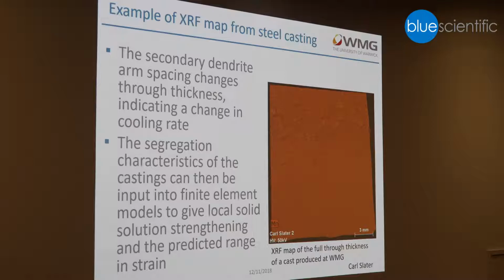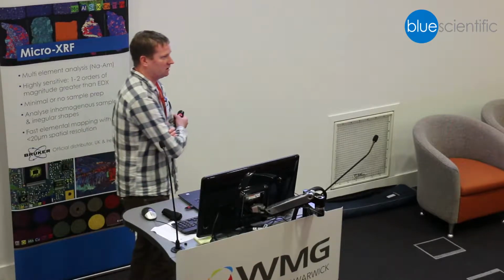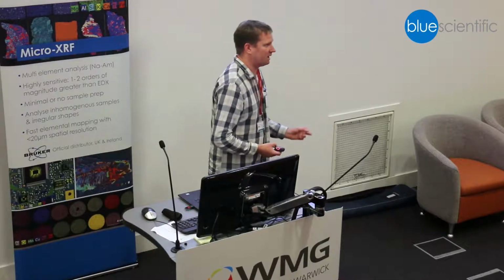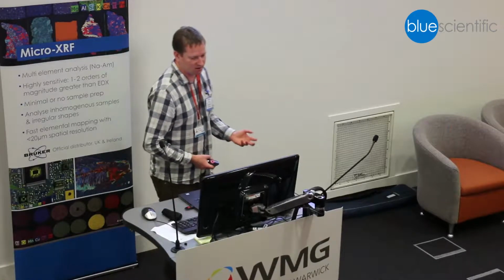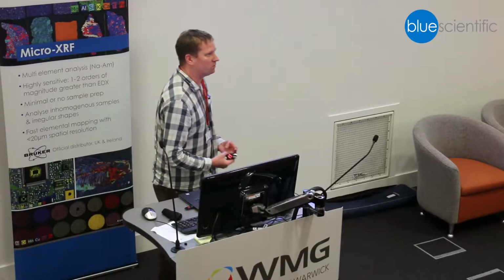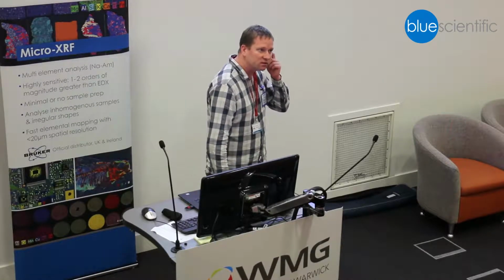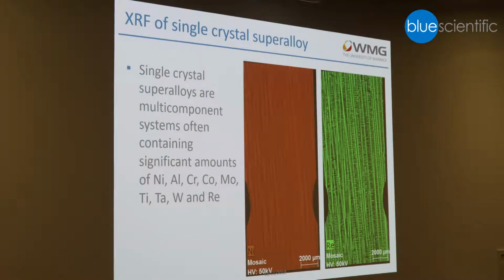differences in local strain. We also do quite a lot of work on superalloys, and superalloys are very chemically complex. They typically have a lot of elements in there, and when we do our analysis on these, we often assume that they're homogeneous, and that assumption, as you can see from these XRF maps, isn't necessarily so good.